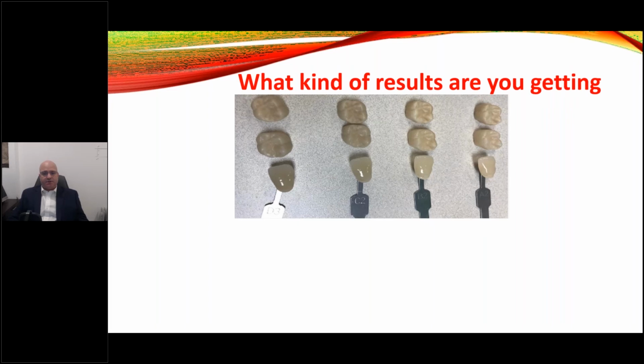Obviously the ones at the top are of higher sintering values. So those are 1500, where the ones below are 1480. But notice how different it is with just a 20-degree difference. So if you're getting these, and this is certainly troubleshooting, and certainly the folks at technical support can help you through this, but it's an education, similar to what we've done with ceramics, where we've learned about ceramics and how ceramics behave and how to actually affect change to get it to act the way we want it to. Similarly, we have to learn with zirconia, and it's a different animal.